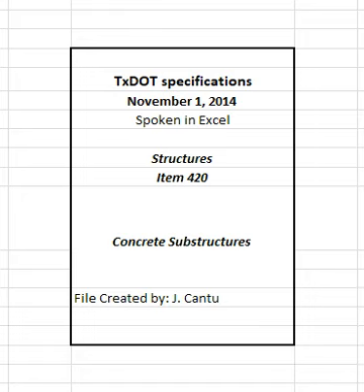Furnish and install 2 pairs of temperature recording devices, maturity meters, or other approved equivalent devices. Install devices to measure the surface temperature no more than 3 inches from the surface. Install devices to measure the core temperature a distance of half the least dimension from the nearest surface near the point of maximum predicted heat. Use these devices to simultaneously measure the temperature of the concrete at the core and the surface. Maintain temperature control methods for 4 days unless otherwise approved based on the submitted heat control plan. Do not use maturity meters to predict strength of mass concrete.